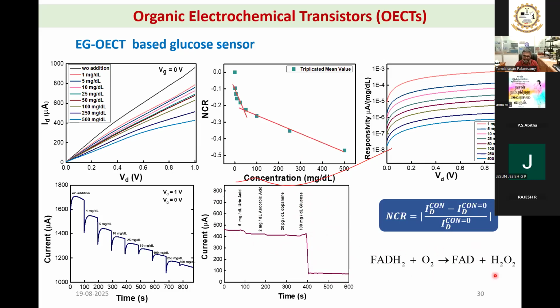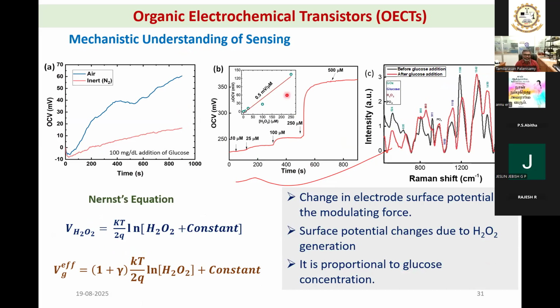And the reaction we have already discussed in the previous study. But one thing is the H2O2 is forming. That is the mechanism we have seen in our previous study. Now we have to prove this mechanism. How? We have taken three different approaches here. One is simply take that electrode and put some H2O2 at different concentrations and see how its open circuit potential changes. Open circuit potential is nothing but the equilibrium potential of the electrode. Now, if you increase the H2O2 concentration, gradually your potential is increasing. The positive potential is increasing, and we have fitted that to a linear profile also. So it means that if your electrolyte has more H2O2, your electrode will produce more open circuit voltage.